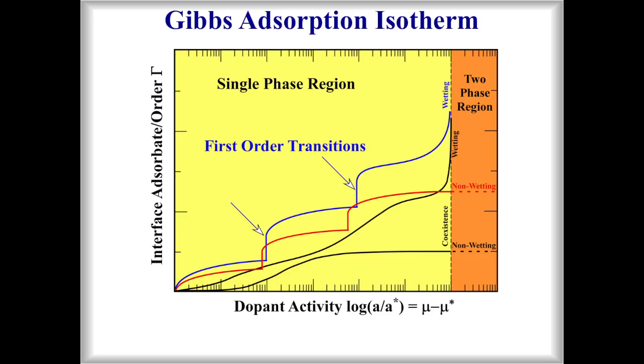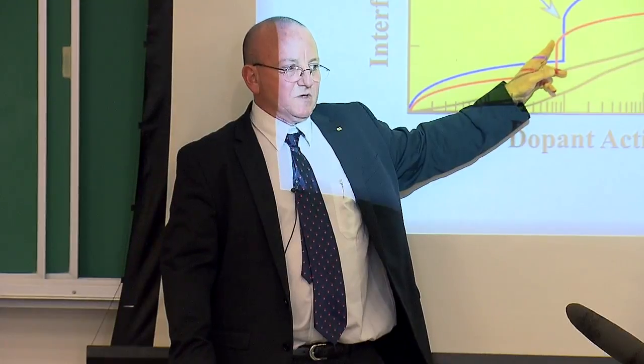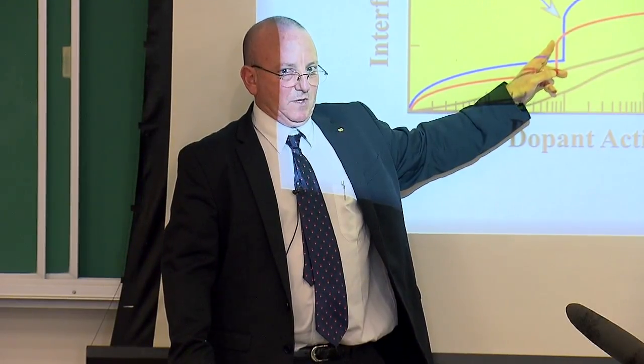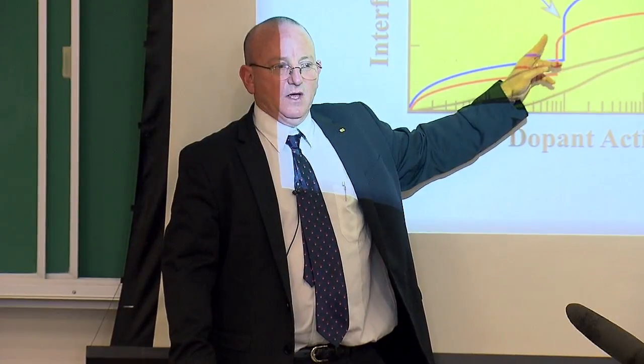I'll skip over the divergence here. So one of the arguments that's been made over the last few years is that there are potential first-order transitions like Kahn's critical wetting point theory, but not between two bulk phases, but at a specific interface itself. So I'm not talking about contact angles here. I'm talking about the energy of an interface as adsorbate comes to it. And here, instead of this nice gradual black line that I've drawn, there's a discontinuous jump in the amount of adsorbate at the surface. And that must mean a first-order transition in the state of that surface. Almost like a phase transformation of the bulk, but of course this can't be a phase because we're talking about a surface. We wouldn't want to use that word, ever.